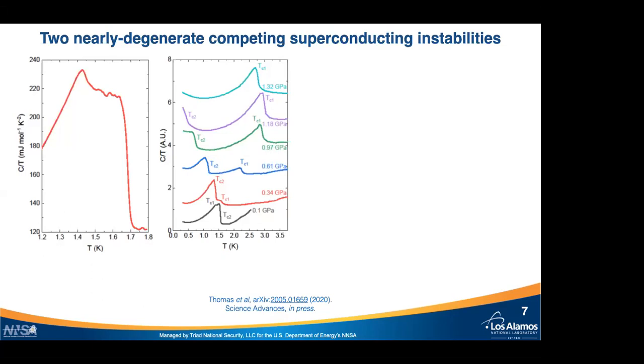You can see that TC2 starts to lose entropy, and TC1 starts to gain entropy. So this is really screaming to us that there are two transitions and they're competing. One is suppressed under pressure and one is enhanced under pressure. So we can now write down a free energy, and this is not a microscopic model. This is just a very phenomenological model of two competing order parameters, psi1 and psi2, and epsilon here is pressure. At some pressure when epsilon is 0, which means experimentally roughly 0.2 GPa, these two transitions are accidentally degenerate. But as you increase pressure, one of them, psi1, is enhanced and psi2 is suppressed.